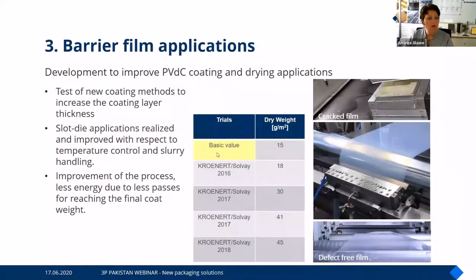In addition, we also looked at how we can improve the process itself. Whoever is familiar with PVC coating knows that the basic value in the past for coating PVC with one layer was 15 grams per square meter, which means if you need to coat 90 grams per square meter due to a medical pharmaceutical product, you will need to run through the machine multiple times. And to improve that, we also did a lot of development with Solvay. And today we have already reached 45 grams per square meter, which means with the optimization of the process, with a much better drying performance, with a much better understanding of the process, we were really able to triple the coating weight with one layer, and this results in much better handling in a coating machine.